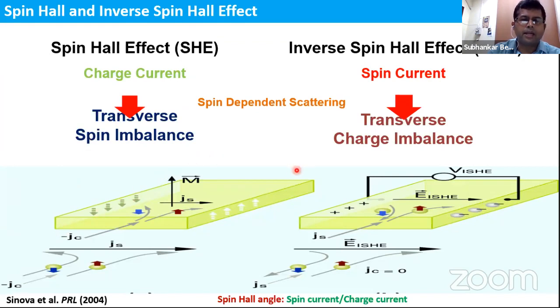So the spin Hall effect: you have a metal and you pass a charge current, and because of this, there is a sort of imbalance in the potential for different spins, so they will move to different edges of the sample. So there will be, let's say, up spins agglomerating at this edge, and the down spins at that edge. So you have a net spin current, and that's basically the spin Hall effect. But unfortunately, you cannot really directly measure the spin Hall effect because measuring spins is very challenging. Well, you can measure optically, but it's much more complicated, I would say. So to overcome this problem, you can use the inverse spin Hall effect, which assumes a similar concept. Imagine you have a spin current in a material, and the charges will now agglomerate at the edges, and that will lead to a voltage, which will directly give you information on the spin current.